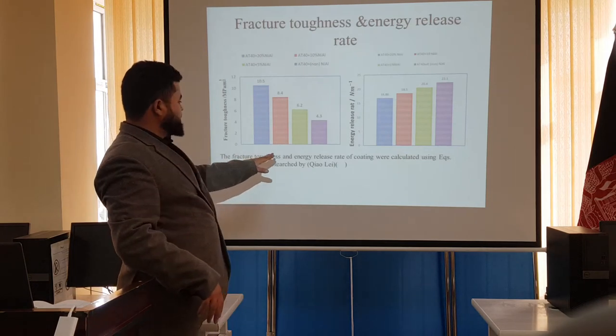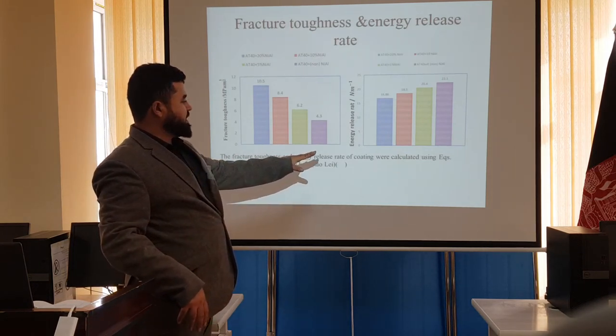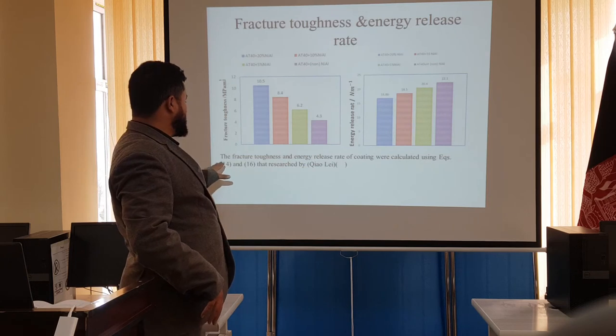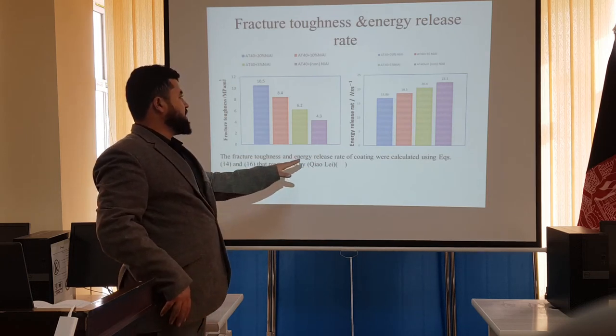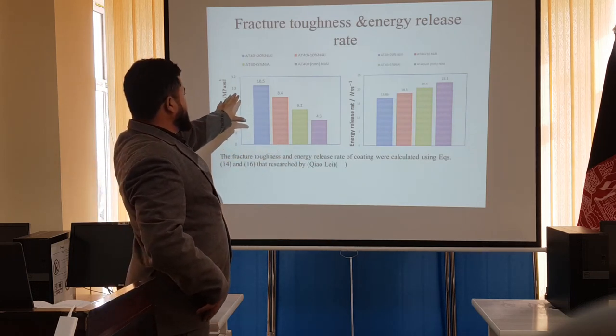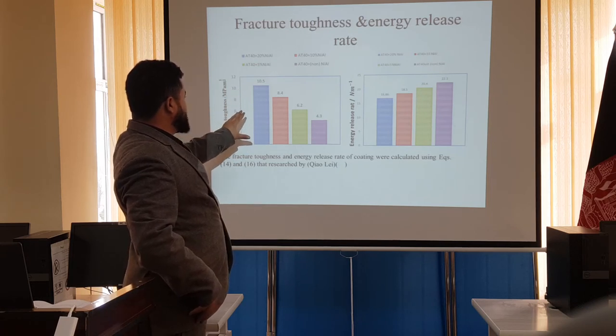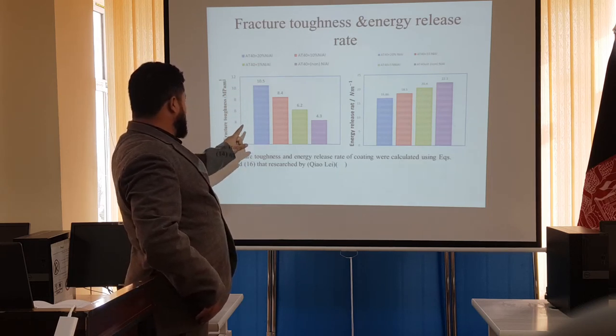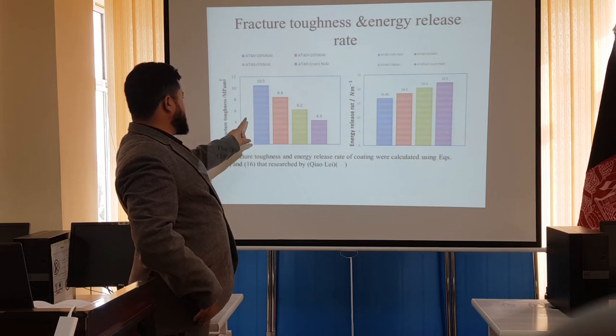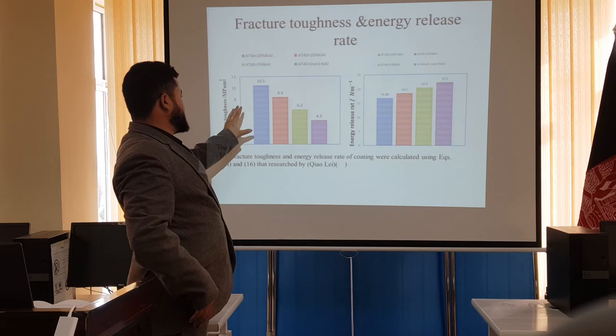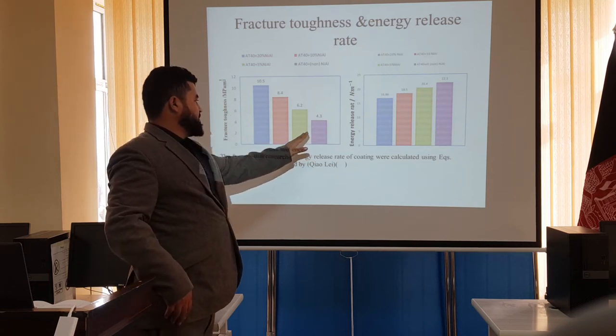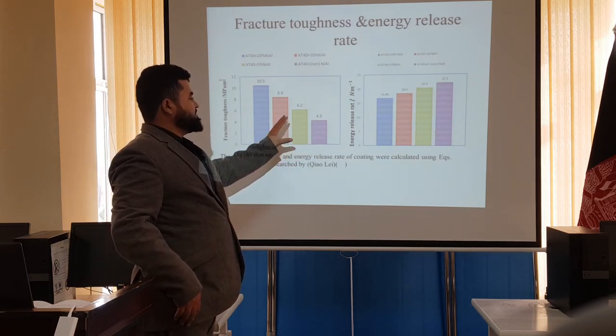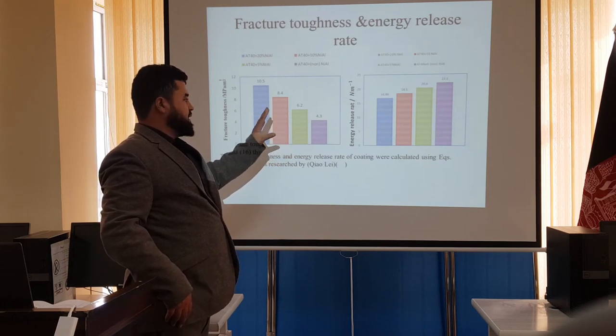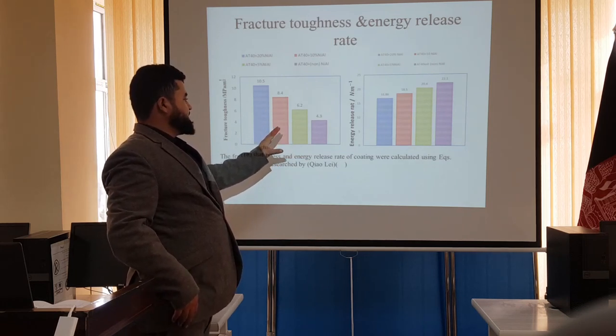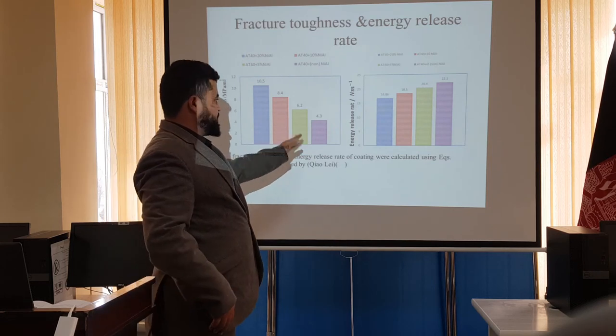The fracture toughness and energy release of the ceramic coating were calculated using equations 14 and 16 researched by Qiao Lei. After analyzing and calculating by equation, we find the fracture toughness of 8040 with 20% nickel aluminum is 10.5, then 4.3 for 0%. It means 8040 without nickel aluminum has poor fracture toughness.